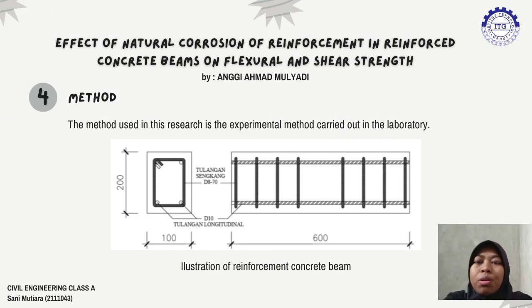Next, the method used in this research is the experimental method carried out in the laboratory, and researchers use beam samples measuring 100 by 200 millimeters with a length of 600 millimeters, as many as 3 pieces using corroded reinforcement and 3 pieces with uncorroded reinforcement. The reinforcement used is 10 mm diameter as longitudinal reinforcement and 8 mm diameter as stirrup reinforcement.